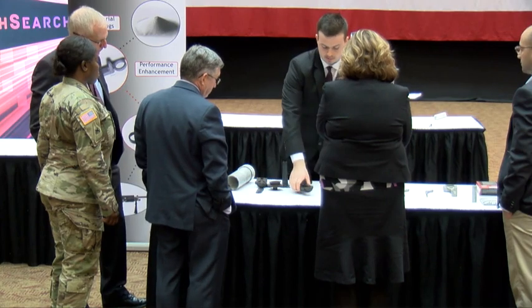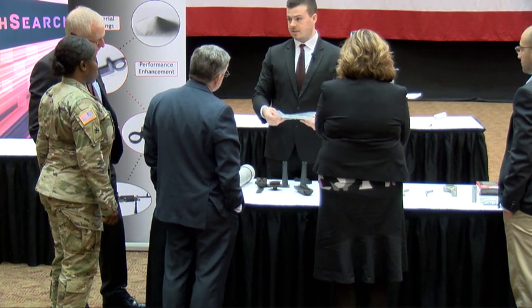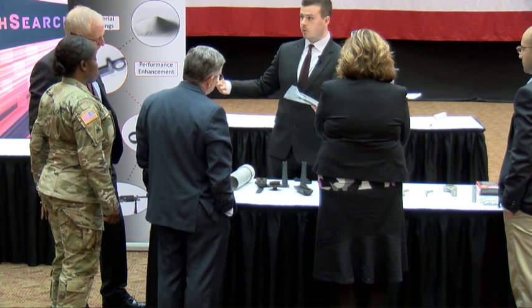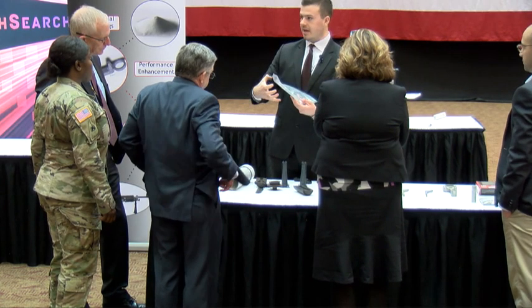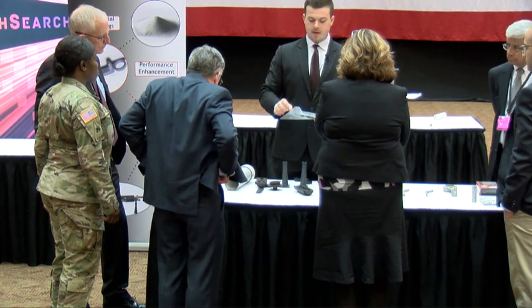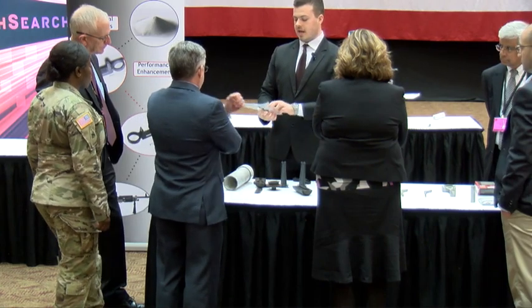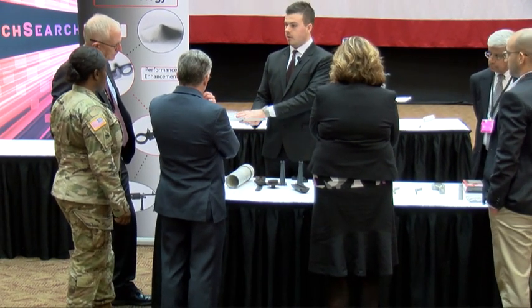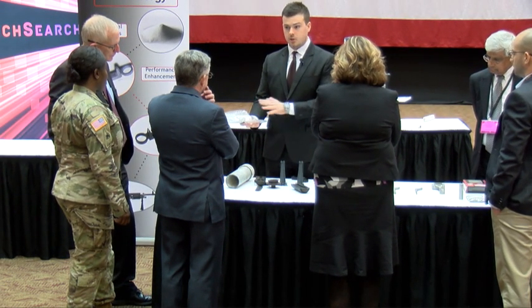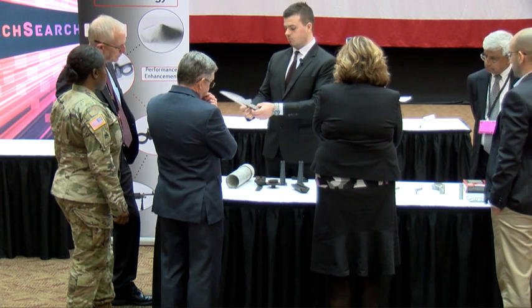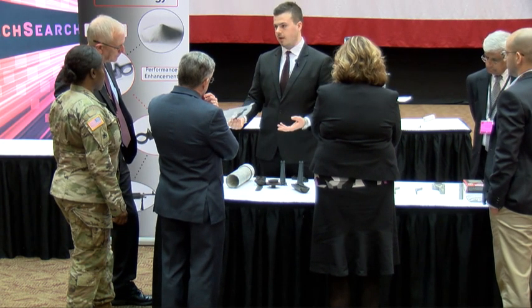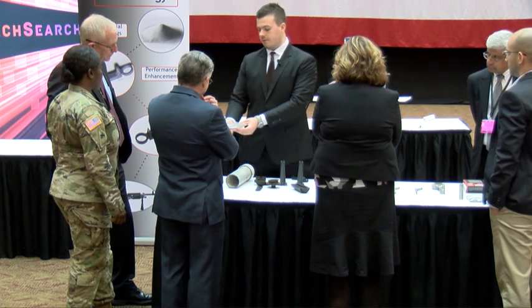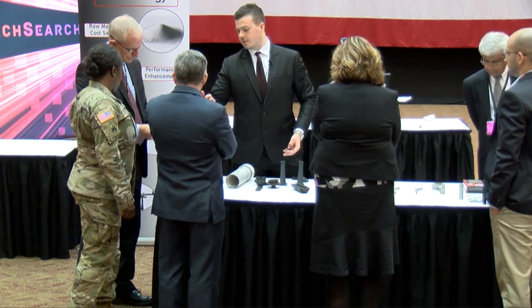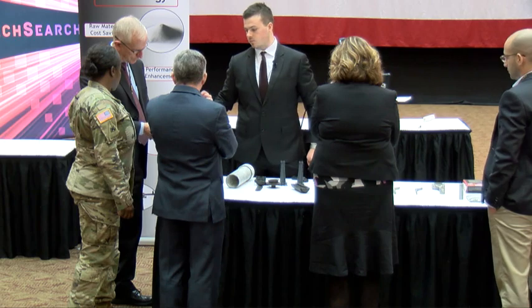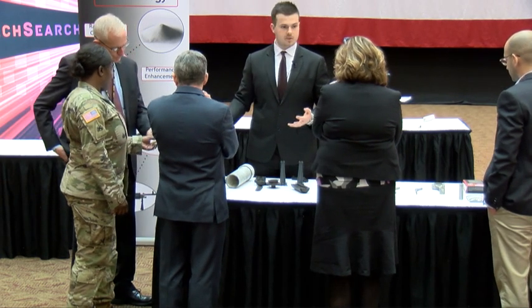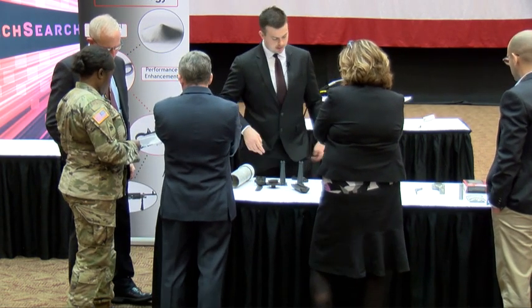This part is then placed into what we call a cold isostatic press, where fluid surrounds the part and is pressed at high pressure. That creates a part that is now surrounded by a bag, tied off, and then another bag to ensure that it's not going to get wet, and then it's relatively strong. Now, granted, this part had to fly here, so it cracked in two spots, but you can feel the strength of this spot, for example, or the other spots where it didn't crack at its weak point. So it's a relatively strong material, but it's not fully dense.